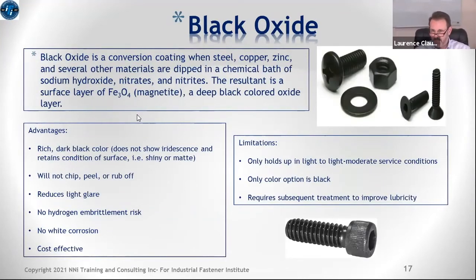All right, black oxide, a quick mention of this. Black oxide is an oxide that gets put on the part when you immerse it into a heated bath of a certain number of chemicals. The result is that you end up with an oxide called magnetite, Fe3O4, which provides a very deep, rich, very attractive black color. So if you're looking for a fastener that has a really attractive black that's not going to chip away and show what's underneath, black oxide might be a really good choice. Again, it gives you a nice black.